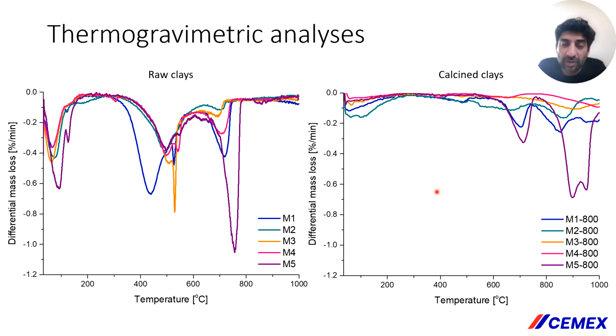Some dehydration was noted up to 250 degrees in the calcined clays, which is expected because we have observed 2:1 clay minerals in the XRD patterns of the raw clays, and we know that these dehydroxylate at temperatures higher than 800 degrees Celsius. In fact, illite is known to persist from complete dehydroxylation at temperatures up to 900 degrees Celsius.